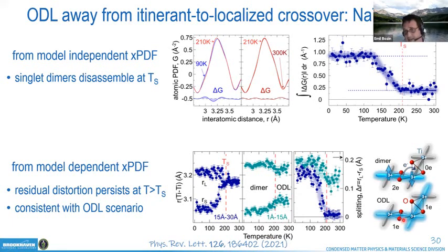And then this gets disassembled to basically obtain 2 ODL-like bonds, which are covalent bonds containing 1 electron. Now, this type of analogy is problematic in this particular case, because we're dealing with a quasi-1D system, and because this type of mechanism would imply a single-valued homogeneous chain with some kind of shorter distance, which is clearly not what is observed experimentally.